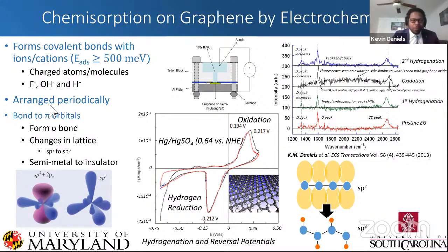And unlike with the physisorption that is kind of random, these are arranged periodically, and they go from these pi bonds to these sigma bonds. So you actually have a change in the lattice. And so we were interested in putting hydrogen on, but there was a clear oxidation peak here. And so we were like, okay, well, can we cycle hydrogen off?